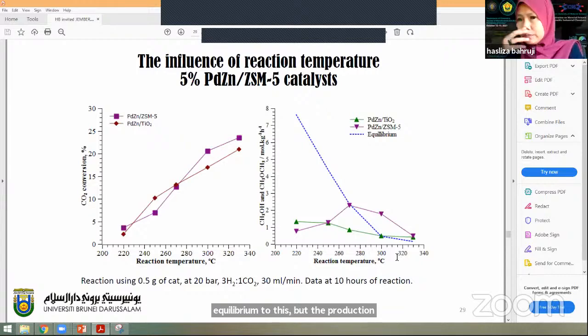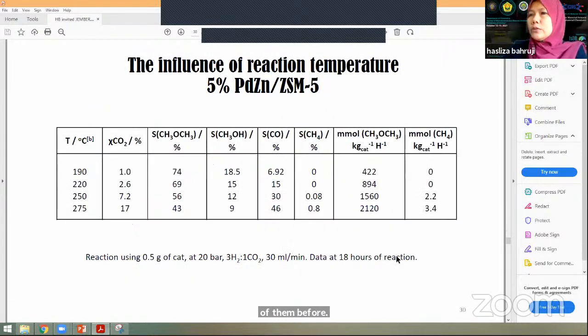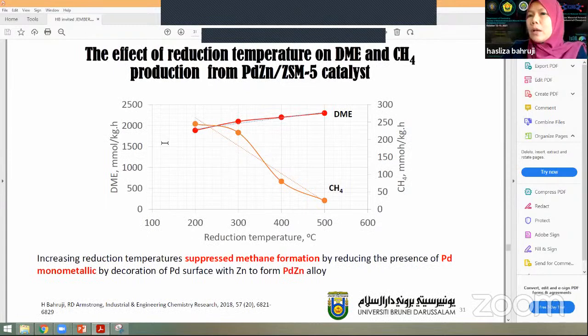So this is the summary of the results so far. We achieved 17% CO2 conversion at 275, and the productivity is actually improved. We got about 2,000 millimoles of oxygenated products compared to 1,700 when we only use palladium zinc on titania. And the same thing as well, when we increase the reduction temperature, we actually maintain the DME production, but at the same time, we remove methane.